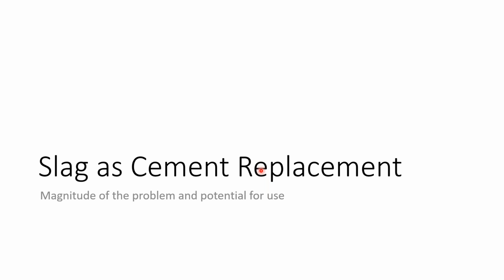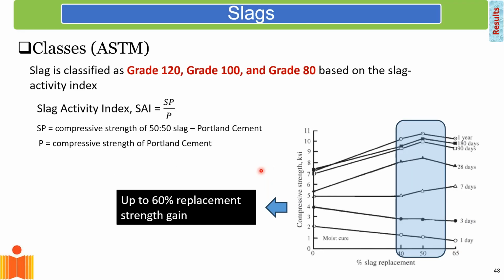Coming quickly to slag, which is the other material that is talked about as cement replacement. In slag we have different reactivity, and just like fly ash, the reactivity of slag varies considerably. And in ASTM, we have this; we don't have this in the BIS standard. Grades are specified. They go from 80, 100 to 120, depending upon the reactivity of the slag.